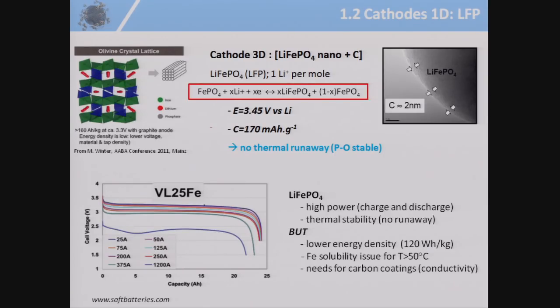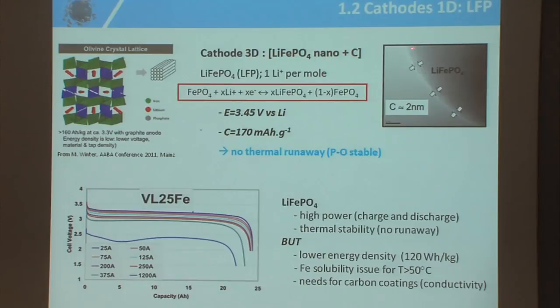The thermal stability is good, but there are 3 main drawbacks. First, you lose about 300 millivolts as a medium cell voltage, so that the energy density is about 30% less or even more than lithium-ion batteries based on NMC materials, only 120 watt-hour per kilogram. Second, when you heat the system, iron is partially soluble, so at high temperature, these batteries are not really good. And the third one is that LFP is a very insulating material, electrically insulating, so that you need to make what we call a carbon coating here, 2 nanometers of carbon coating to make it conductive. That's another drawback. But really, LFP batteries are lower voltage, lower energy density, fast recharge rate.